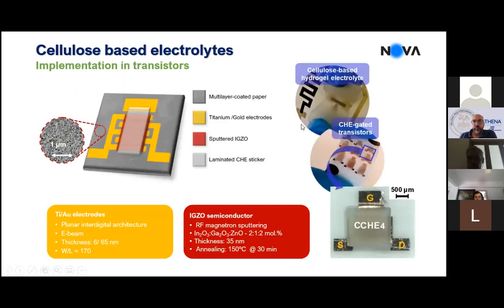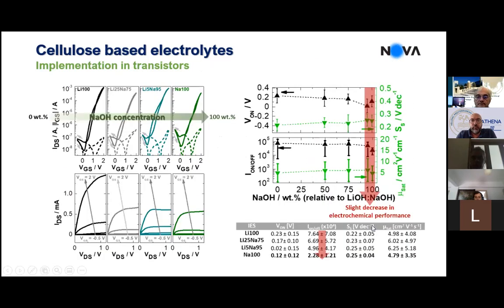Okay, so you see here an example of the transistors with the electrolyte on it. Here a magnification, you see a membrane placed over the transistor. I will not spend too much time on this. Also, this is just a comparison on the performance between membranes that were created with lithium and sodium hydroxide. If you just compare the mobility, that is typically the fingerprint of the transistors, this is not so different. The problem with the sodium